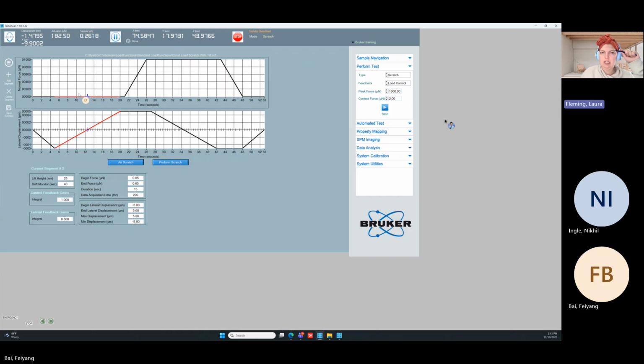And I'll show you what this looks like in the post-analysis. But you can see here that for the first 20 seconds, we are 0 in the normal force. And here, so we're tracing the sample surface, we're in contact, and we go back 5 microns, forward 10 microns, before we load into the sample, do the scratch, and unload. And the purpose here is that this way we have a measurement of the sample tilt before we perform the scratch, so that we can correct our data. Does that make sense? Any questions there?